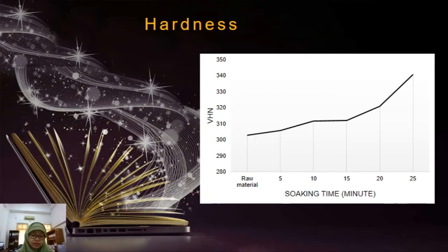A significant increase in hardness of 12.5% was obtained at 25 minutes of immersion with a hardness value of 340.6 Vickers hardness number. The increase in hardness is due to the emergence of secondary carbide formation with lamellar forms. The increase in hardness in the FeCrMn alloy is due to the emergence of secondary carbide with lamellar forms and large grains of austenite, because the cryogenic process does not cause the appearance of a martensite structure.